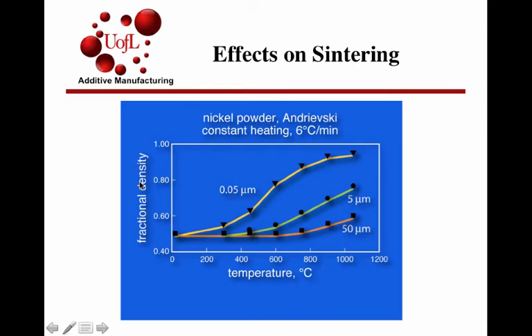Here is a plot of the fractional density as a function of temperature for nickel powder plotted for three different particle sizes. Density increases as temperature increases, so there is more thermal energy that allows for consolidation. Also, surface area plays a big role. Surface energy and its minimization is a driving force for atomic motion to occur. Finer powders sinter densify to a greater extent at any given temperature. These have important ramifications for 3D printing processes as well.